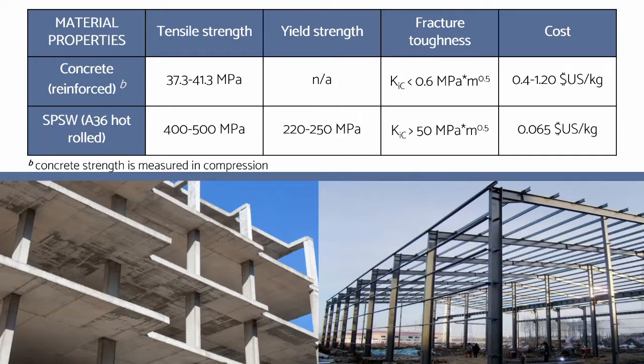As seen in the table, SPSW's ultimate strength is between 400 to 500 megapascals, compared to the concrete's ultimate strength of 37 to 40 megapascals. This allows the steel plate shear walls to experience more load before failure, and in turn resist a stronger earthquake. Additionally, as seen in column 3, SPSW has a much higher fracture toughness of 50 compared to concrete's 0.6, which means SPSWs are more ductile and less prone to cracking than concrete shear walls.